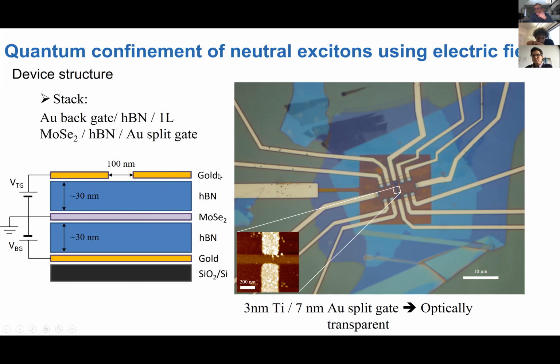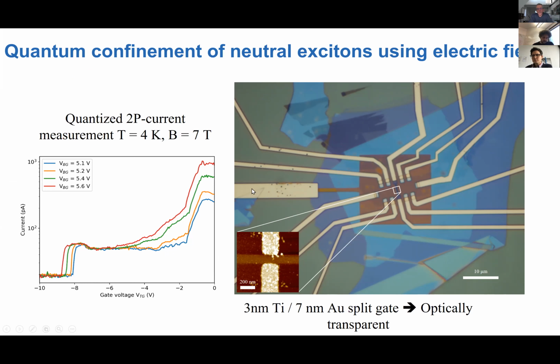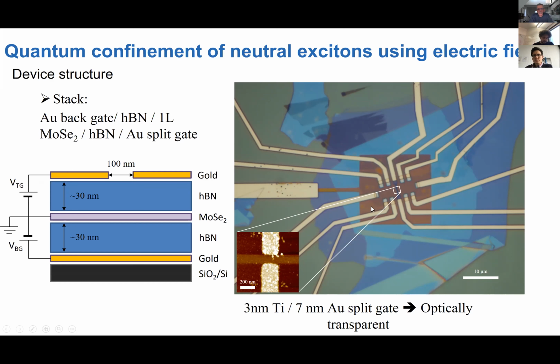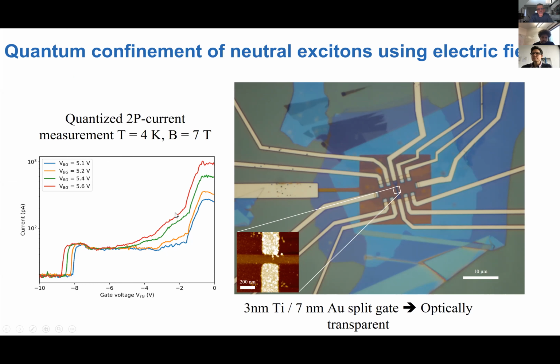In this case, though, instead of graphene, we have gold gates in the structure, which actually reduces the quality a bit, but not in a dramatic way, okay? So such a device is a quantum point contact-like device. By changing the gate voltage, we can make sure that the carriers in this constriction can be depleted out. And that's what you see here. Normally this is a device in which you will see quantized conductance plateaus.